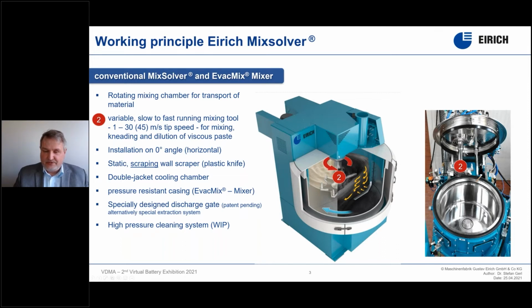The system also allows us to control torque so that we can produce excellent dry mixes within the machine. We can also do excellent kneading, controlling the torque level, and we can do the slurry making. To prepare the slurry, the machine is put into a horizontal position, because some of the machines developed in the 70s were inclined, but the liquid will not flow up the hill. An additional feature is the wall and bottom scraper, designed as a scraping element for the lithium-ion battery industry, with plastic knives taking away all adhesions on the wall and bringing them back into the slurry to make sure that all the solids are really well dispersed inside the machine.